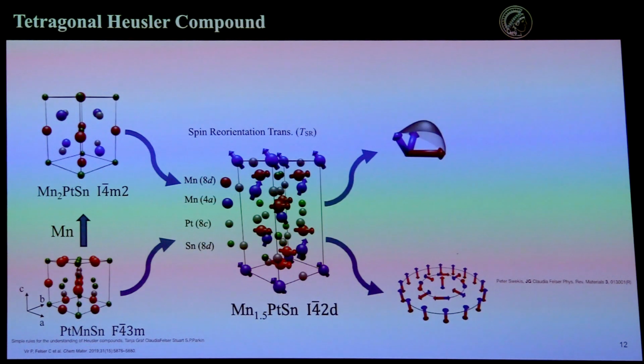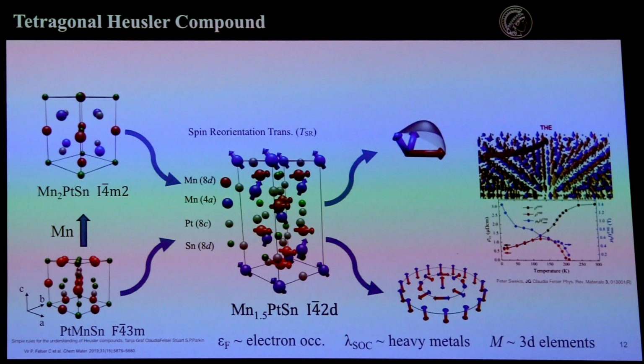And so from this, you get two types of transitions, which was not so easy to understand what the origin is, but we will show what the origin is quite soon. You get this non-coplanar texture, and you get this antiskyrmion in finite fields. And this, of course, will lead to one of these Berry curvature responses, which we call the topological Hall effect. So as you apply a current to this, not a very large current, these electrons get deflected by this magnetic field of the skyrmion, and you get some topological Hall effect that depends on the temperature because of the spin reorientation transition.